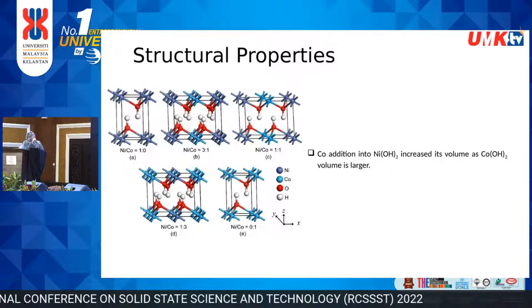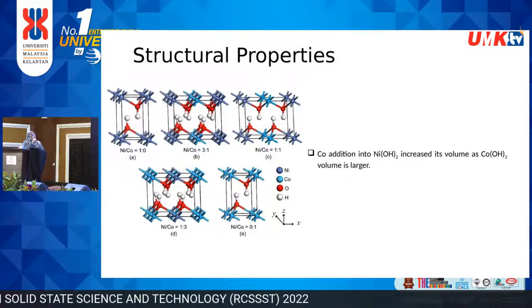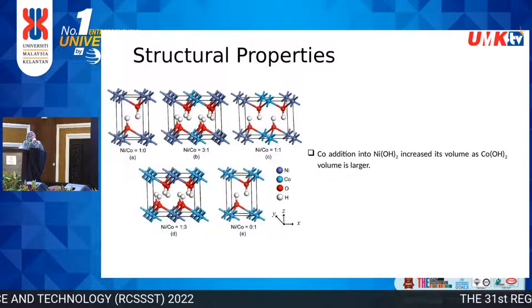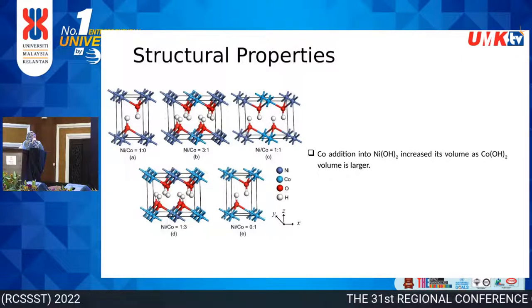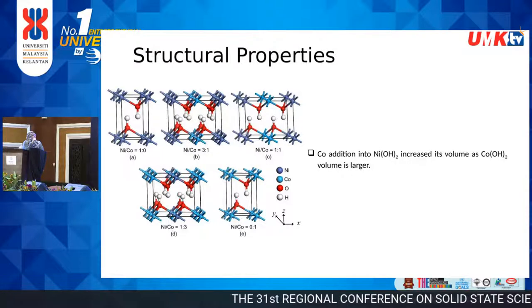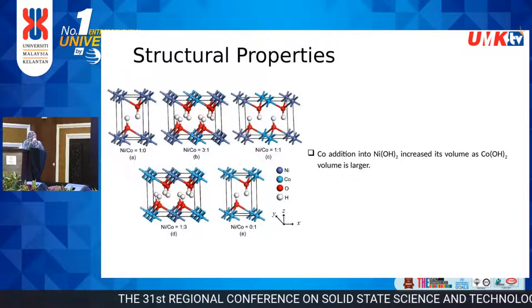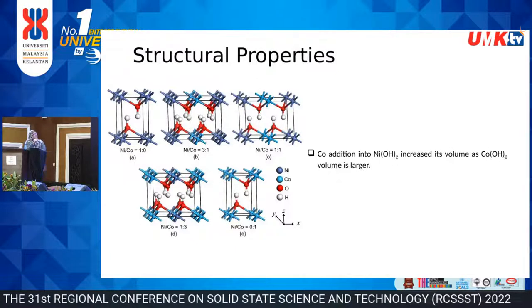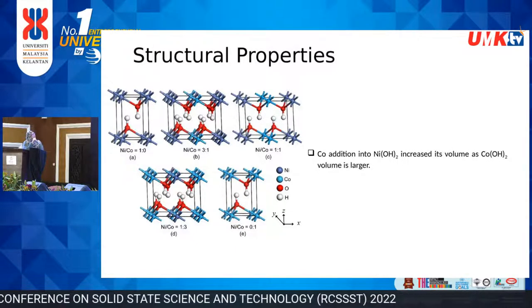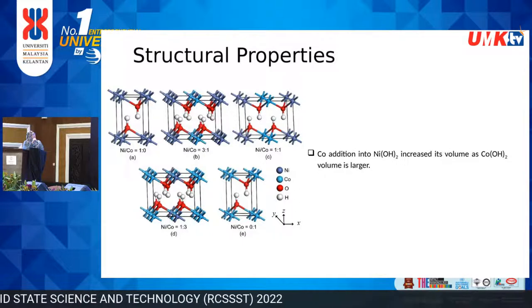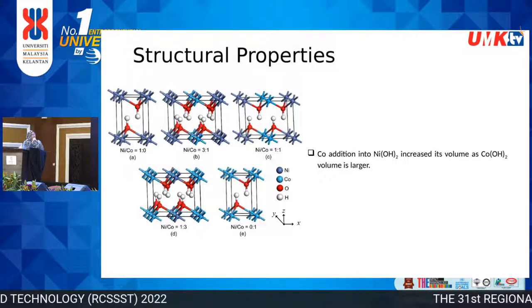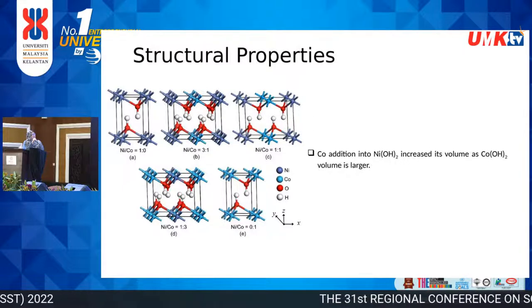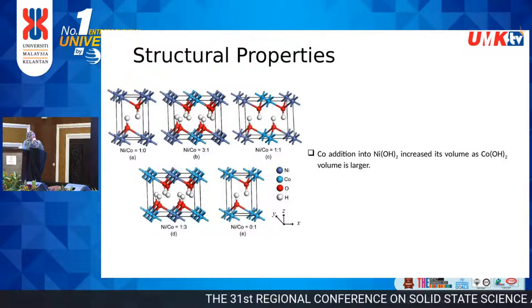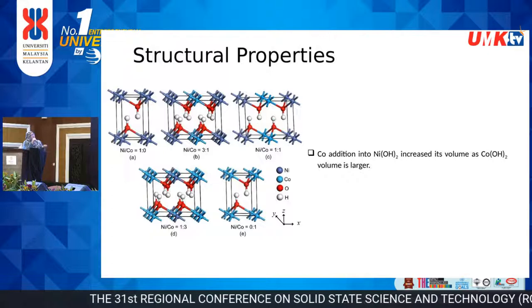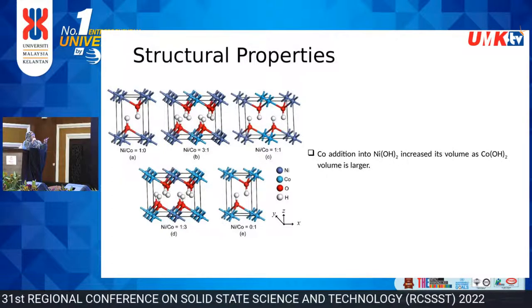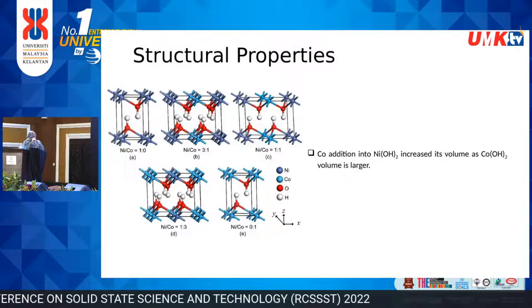This is the structural properties calculated by GGA PBEsol. We have nickel to cobalt ratios of 1:0, 3:1, 1:1, 1:3, and 0:1. From this table we can see that by adding cobalt to nickel hydroxide, the volume increases because the cobalt hydroxide volume is larger, as you can see from the table.